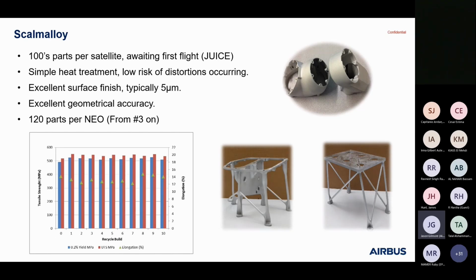But obviously you can see here that there's no real drop off, or I would say no drop off at all. There's a small fluctuation. And coming back to Nick's great presentation earlier, talking about powder handling, there's some IP we've achieved over the years and fed back to AnyShape about good and robust powder handling. You will get a drop off eventually, but the longer you can keep the powder good to go, the better. And also the elongations, you can see the triangles, everything's between 12 and 14% elongation. So some really good material properties and very, very repeatable. And this is the type of data we can present to our customer to show that we've got a highly repeatable process.